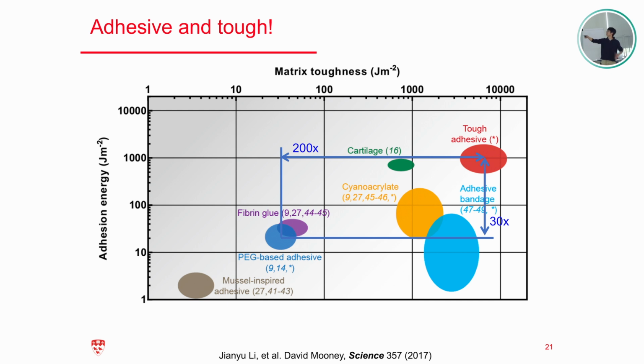As you may also think, how about the adhesive band-aid? It's made of very tough elastomer, so it should have very good matrix toughness. But as you can see here, the bonding of this elastomer, the adhesive band-aid, with the tissue is quite limited and very weak, based mainly on physical interaction. The adhesion energy of the adhesive band-aid is much lower than our tough adhesive.